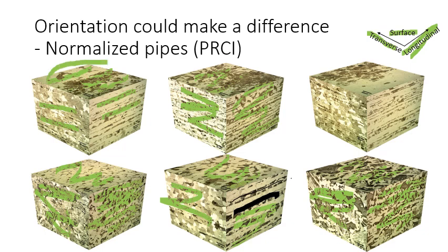So how do we overcome this deficiency or this potential problem? Probably the best approach is evaluating multiple fields. Similarly, in the upper right-hand corner, we see some banding in the longitudinal direction, banding in the transverse direction, and we see these splotchy regions with a lot of the dark phase and then almost none of the dark phase.